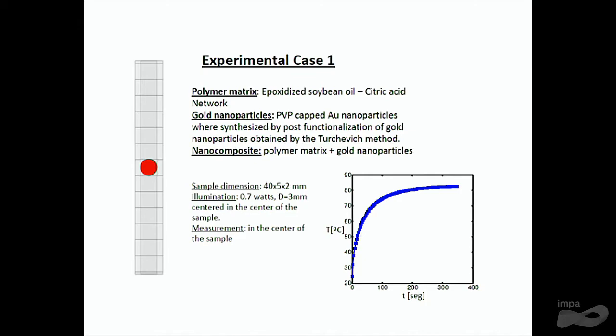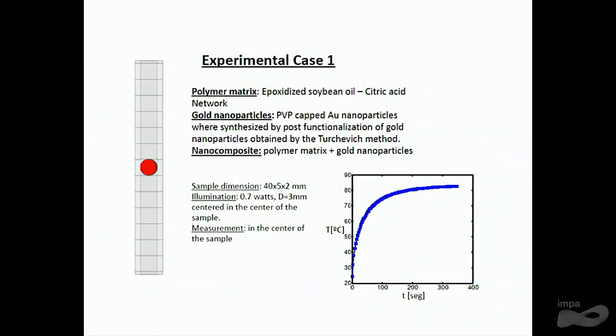We build the polymer. We include the nanoparticles. So we made what we call a nanocomposite. It's a composite material made of polymer, transparent, and gold nanoparticles in a very small quantity. You don't realize that they are there, not visually, and they don't change the mechanical properties of the material. The sample dimension in this case was larger than the ones I presented earlier. And the form of the light spot is also different. This is probably more realistic, because normally the spot of a laser beam is circular. This is the temperature evolution that we actually measure in the center of the sample.